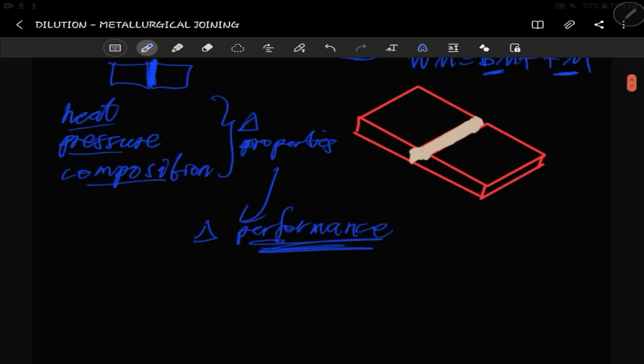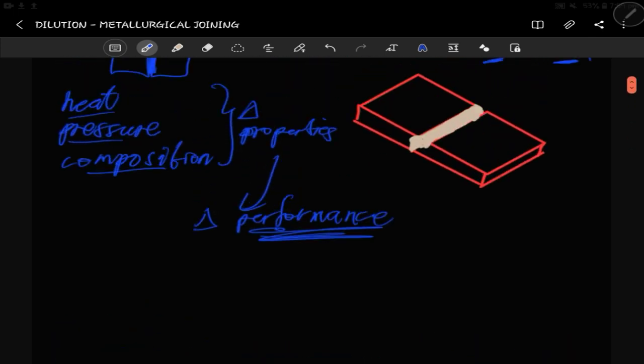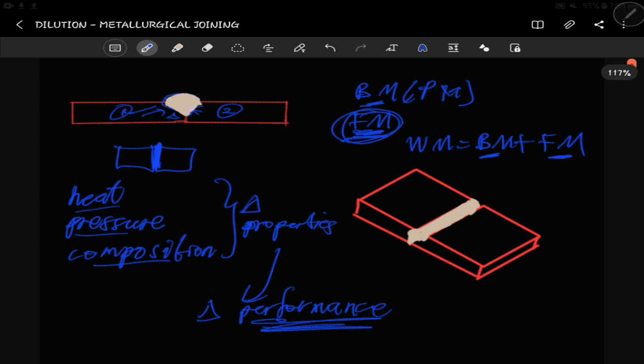So basically, dilution is a change in the chemical composition of the filler metal. We have a filler metal, and some of the base parent metal diffuses into it and mixes, and then it forms something new. So dilution is the change in the chemical composition of the filler metal due to admixture of the base metal in the deposited weld bead, and there's the weld bead as we're seeing.